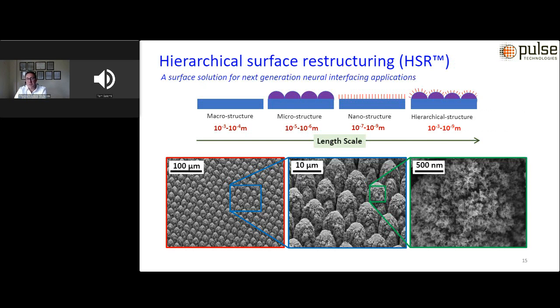But what is the solution? What is it that we're offering? What is hierarchical surface restructuring? Hierarchically structured surfaces exhibit topographic features comprised of varying length scales: coarse scale structures several microns in size, in a range of about 10 to about 100 microns, and a finer structure subset on top of the coarse structures in the range of a few nanometers to a few hundred nanometers in size.